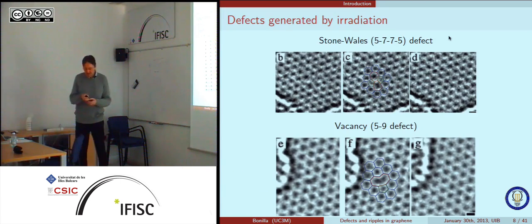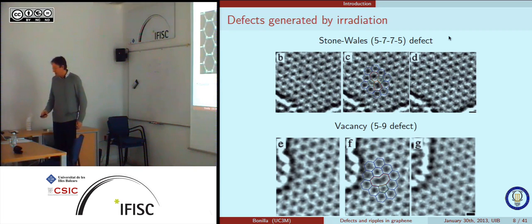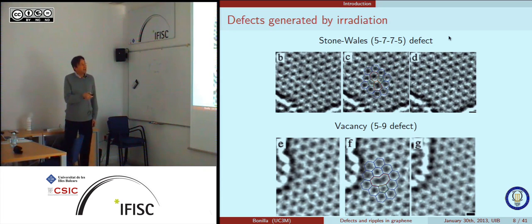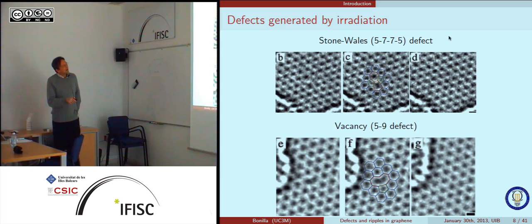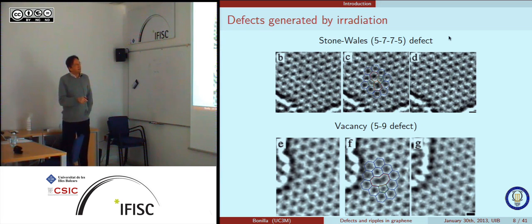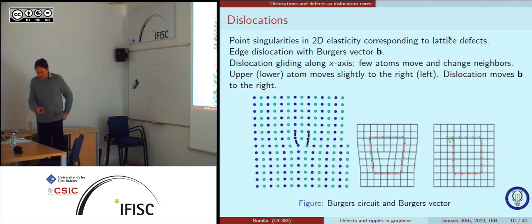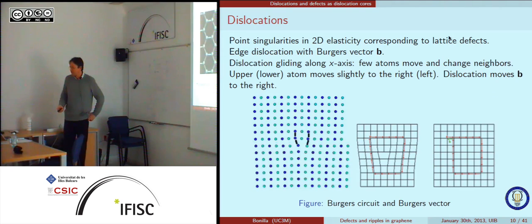Let me just say something. If you look at this view graph carefully, and you start at some point, move around in a circle and go back, you discover that you get the same number of bonds from the beginning to the end as if no defect were there. That tells you that what is going on here is related to dislocations. It would mean that the Burgers vector around this defect is zero. And that's one important thing that we use in our theories.